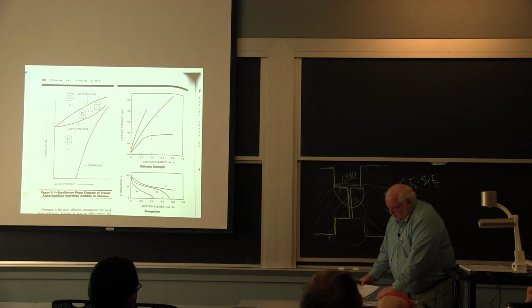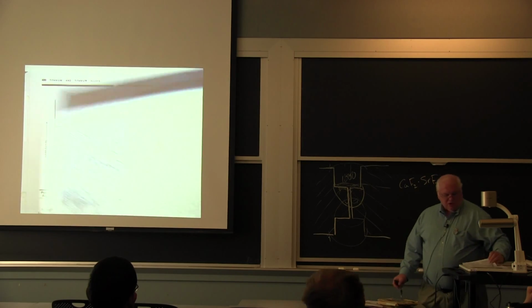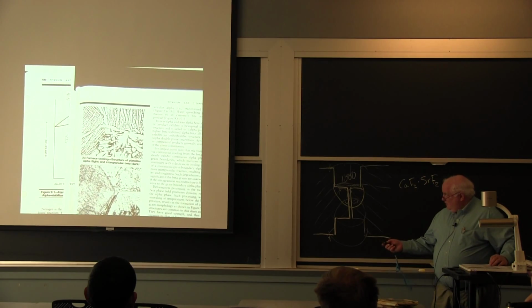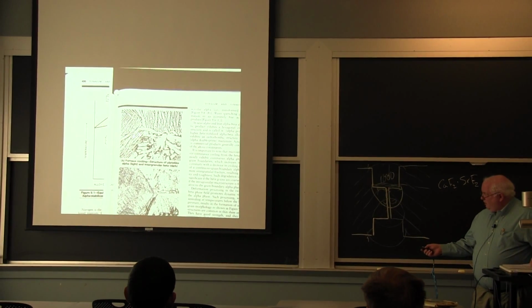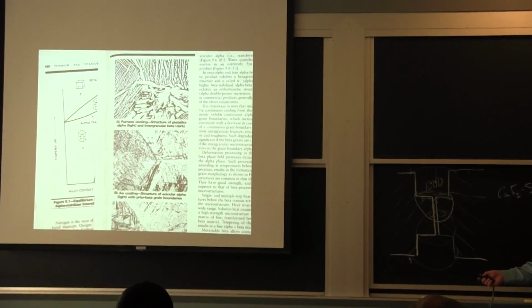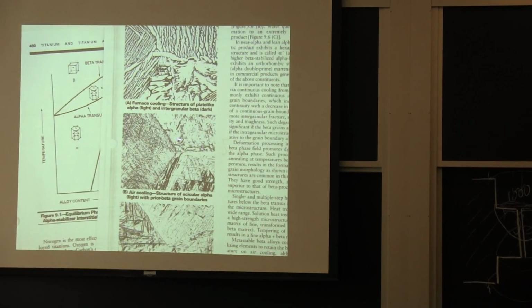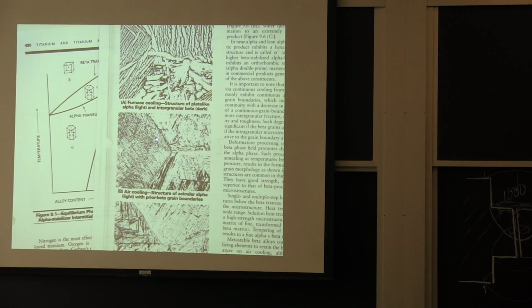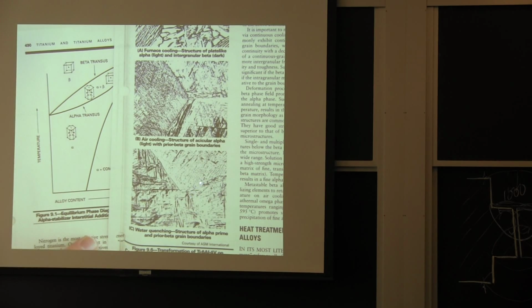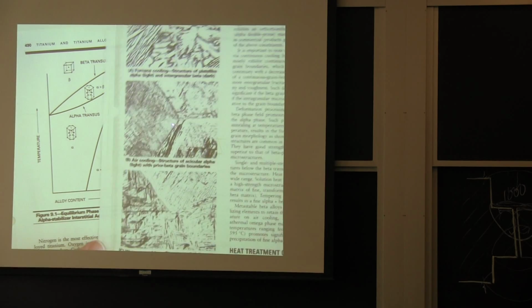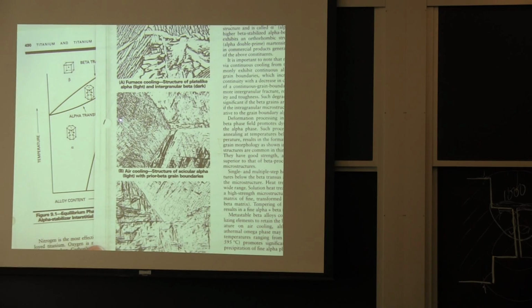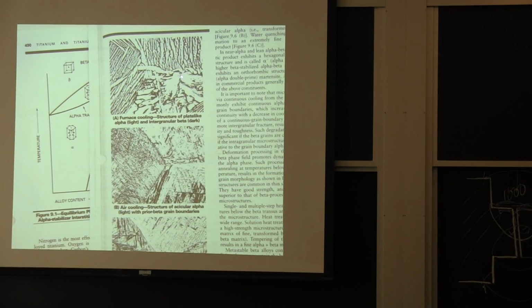No, what you get is what we call Widmanstatten structure. Ta-da! This is slowly cooled titanium 6 aluminum 4 vanadium, and at the grain boundaries you'll get some alpha and then you'll get some beta and alpha in here going different directions. If you cool faster, this is furnace cooled, air cooled, this is basically what you'll get in a weld, and it's ultra fine compared to this. And if you water quench, you'll get something even finer. It turns out this is super strong because of the fine structure compared to the furnace cooled.